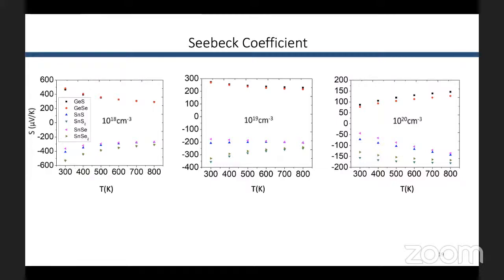For tin selenide, the absolute value is increasing slightly at the 10 to the 19. But at the 10 to the 20, an increasing trend for all materials in the Seebeck coefficient in absolute values is observed. And due to the interrelationship between carrier concentration and Seebeck coefficient, we notice as doping level increases, the Seebeck coefficient decreases, in some cases dramatically.